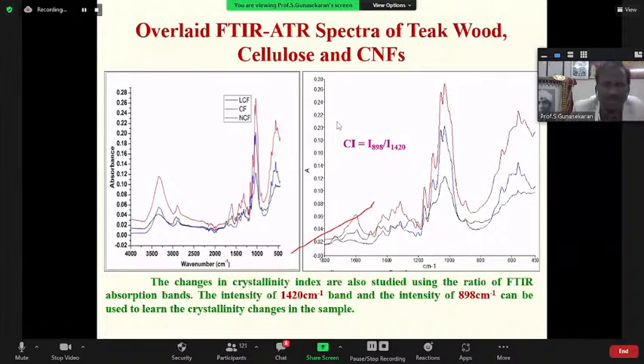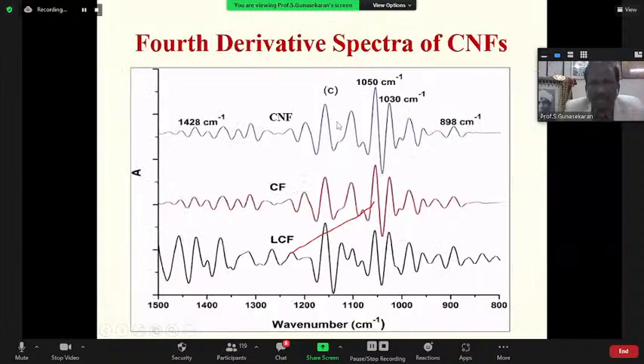The first one is lignocellulose fiber, cellulose fiber, and this nanocellulose fiber using chemical synthesis. So there is a CI, crystallinity index, 898 by 1420. This is a CH2 deformation vibration, asymmetry vibration. This is a scissoring vibration. So with that, we are able to get the factor, that is the value. You see, for LCF, cellulose fiber, and cellulose nanofiber, we are able to get the maximum crystallinity index here.